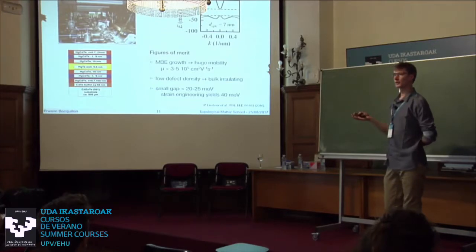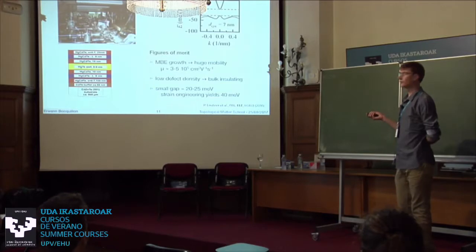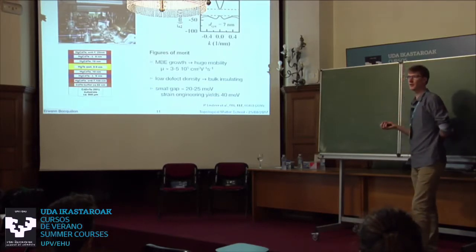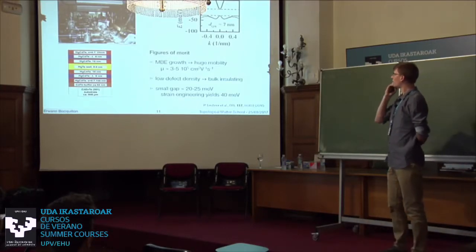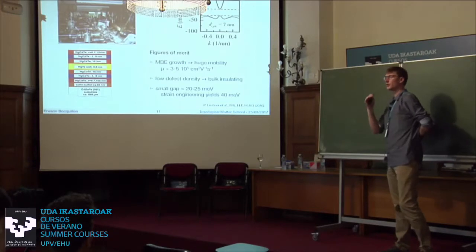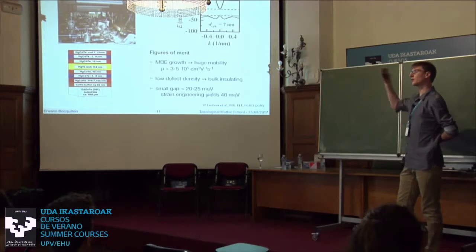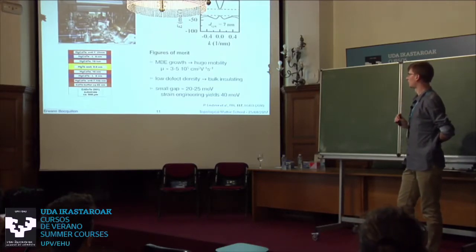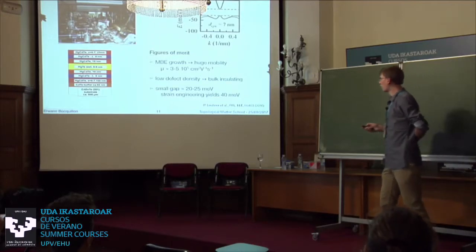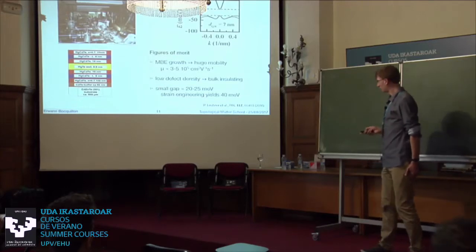But also some compounds like the bismuth families also have a much, much larger inverted gap of the order of hundreds of millielectron volts. So we're very far from that, which means that we need to be very careful when tuning the gate voltage and so on. Tuning the density in the gap is rather difficult and will easily connect to the valence band and to the conduction band. So the good thing is high mobility, the bad thing is very small gap, to summarize.